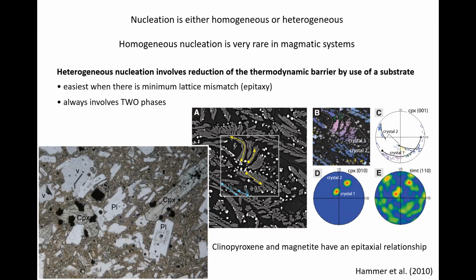Right, so nucleation, primary nucleation, is what happens when you haven't got any grains of that particular phase that you care about. So they're the first crystals to form, and it can be either homogeneous or heterogeneous. Homogeneous is when the nucleation just occurs in the bulk magma. You need a really large undercooling for that, and you need no possible substrates on which it could nucleate. So homogeneous nucleation is actually quite a big ask in a noisy, dirty magmatic system. So heterogeneous nucleation is going to be the norm, and heterogeneous nucleation has got a smaller overstep that's required compared to homogeneous because it borrows a substrate. It reduces the thermodynamic barrier to nucleation by using a substrate.